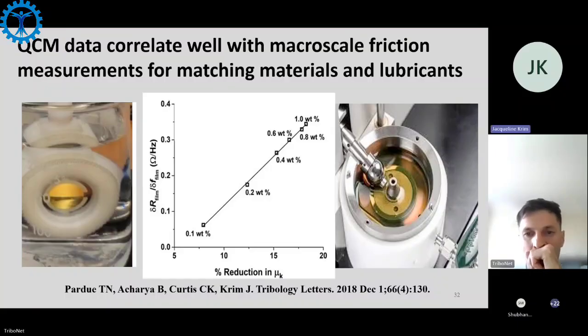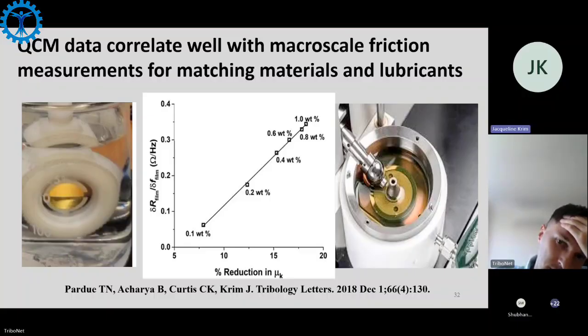So on the right, we used alumina. These were alumina contacts. We wanted things to be free of charge. So these pictures are for representation only. And then on the left, we just did this simple nanoscale experiment. So what are we seeing here? We're seeing that something about the sliding at the interface also shows up on the macroscopic scale. It's not cause and effect as much as if the interface is sliding, it's impacting both scales.